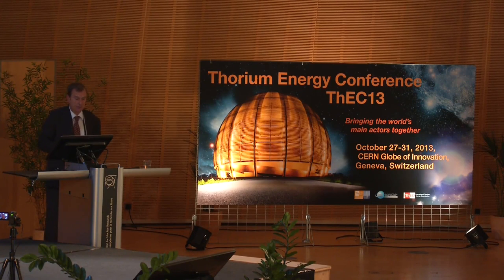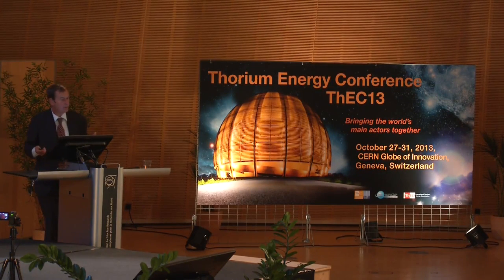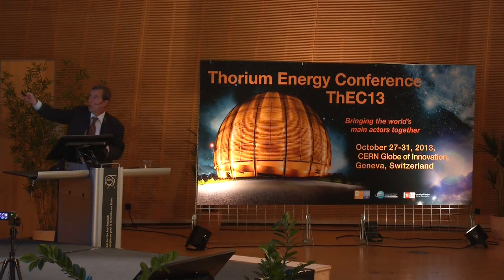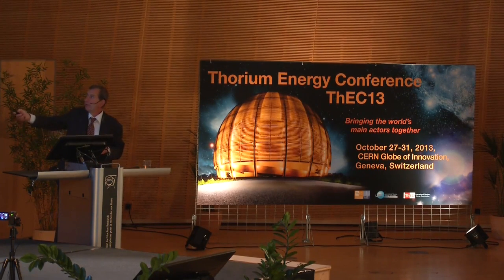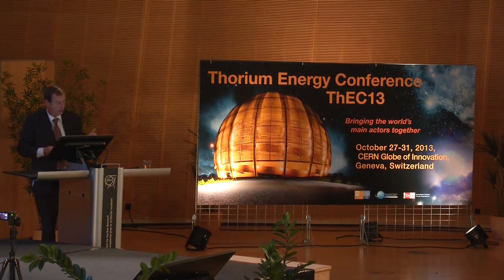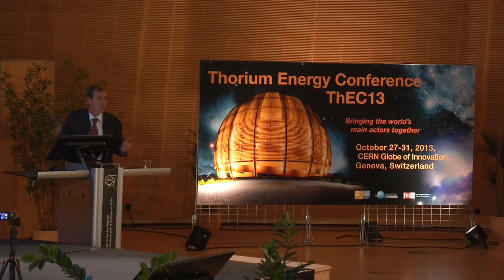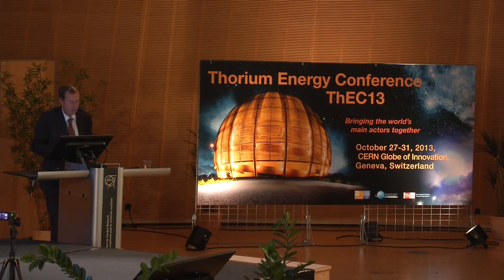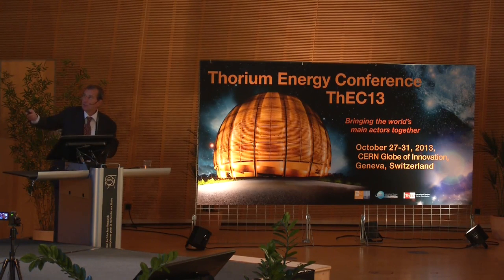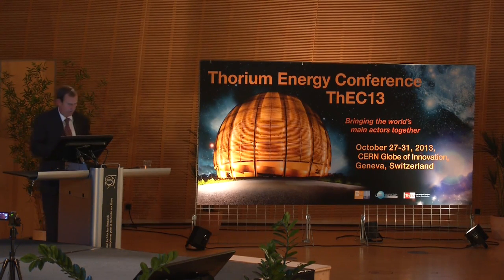Another project financed by the European Commission is the so-called SKIN project. It's still going on, and it's a comparison of solubility values of different elements, in red on all the curves. The example is taken from SKB, the Swedish spent fuel repository, with different graphs corresponding to different compartments of bentonite and granite. And the calculations show that in each compartment, again as expected, the red curve with the thorium is the lowest curve in rate of dissolution.